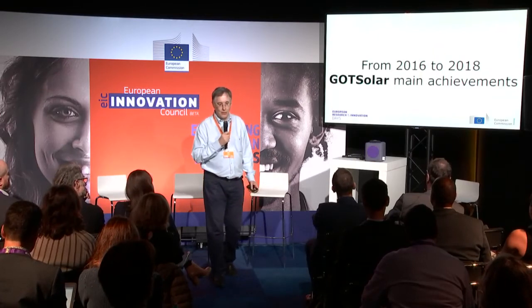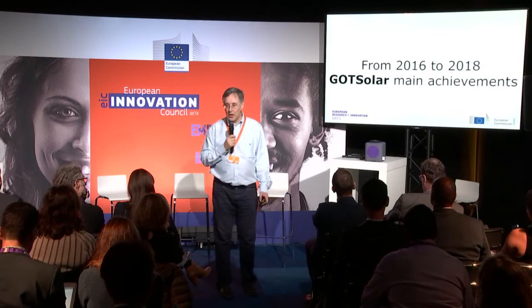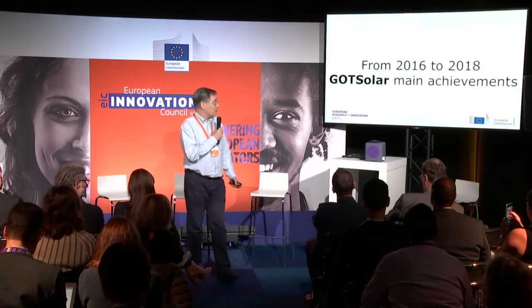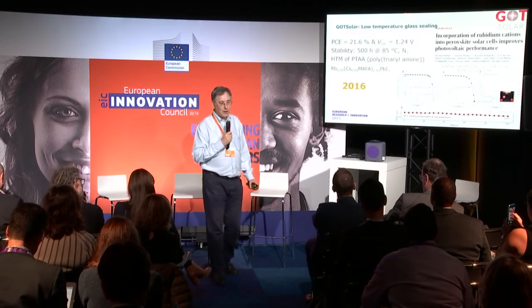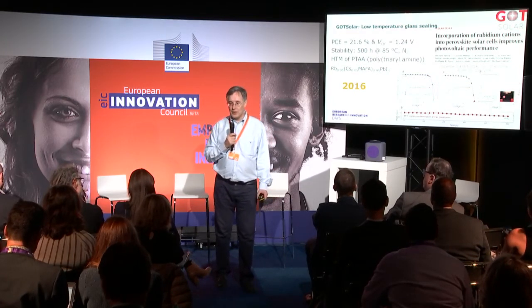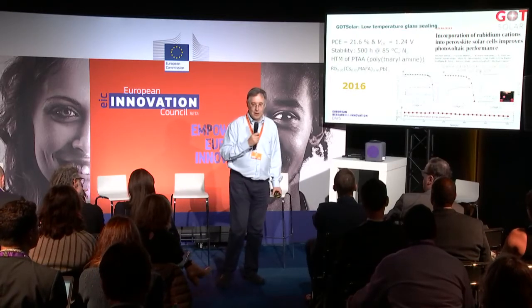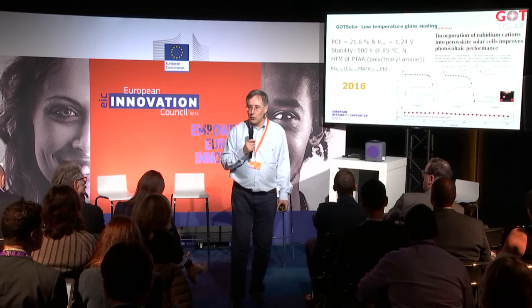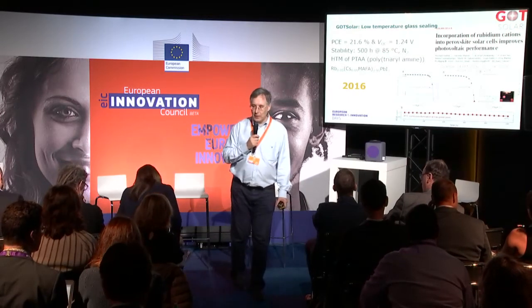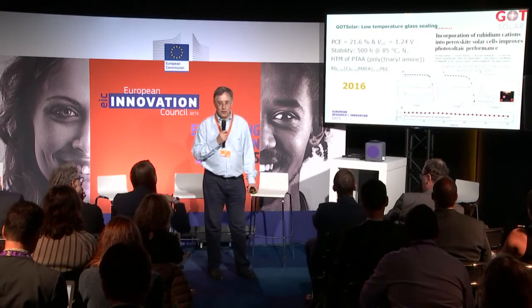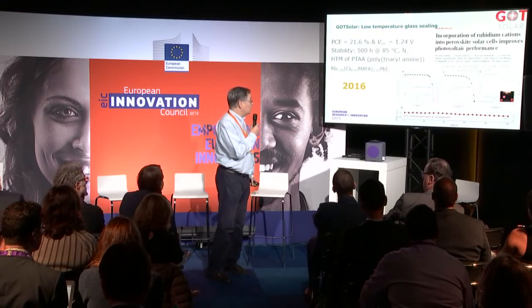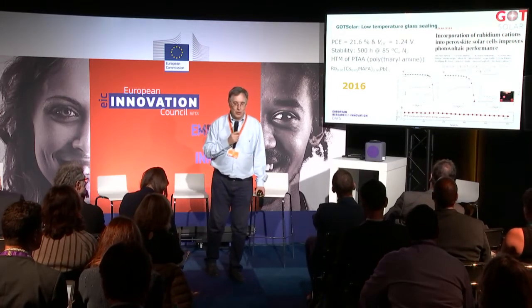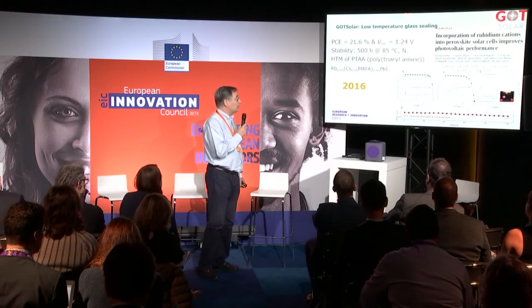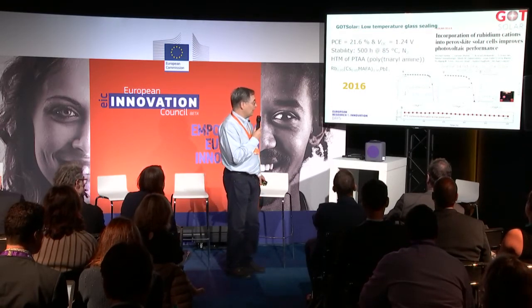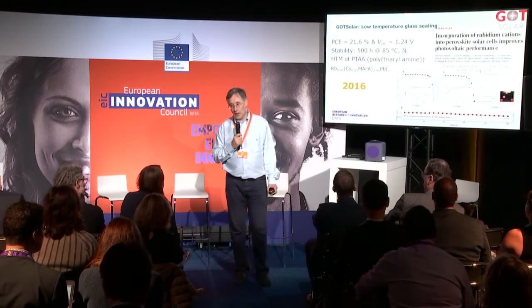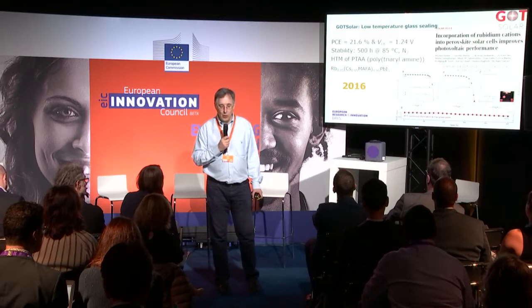So just about GOTSolar, which was the project that sponsored some of these advancements. Within this project, it was possible to demonstrate for the first time in 2016 stable devices, because before they were not stable at all. And for the first time ever, we described a device with 21.6% efficiency, 1.24 volts, which is quite large and very close to the thermodynamic value. And it was stable at 85 degrees for more than 500 hours. But we want more.